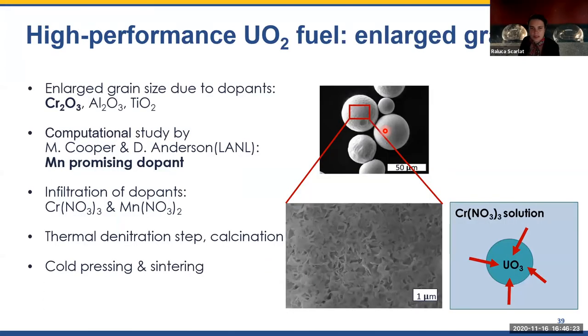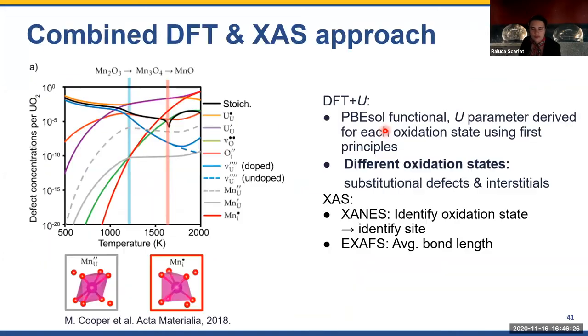So by some mechanism, the incorporation of manganese into the crystal structure or as an interstitial is somehow promoting larger crystals? So Cooper et al. predict that we basically increase the amount of uranium vacancies, and that's very dependent on the temperature. How the manganese is dissolved in the material is temperature dependent, and due to the increase of uranium vacancies, due to the presence of the dopants, it is predicted that we are obtaining larger uranium dioxide grains. But there is no experimental proof for this out there yet.